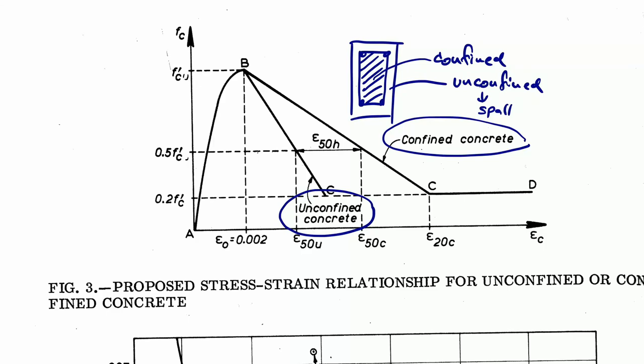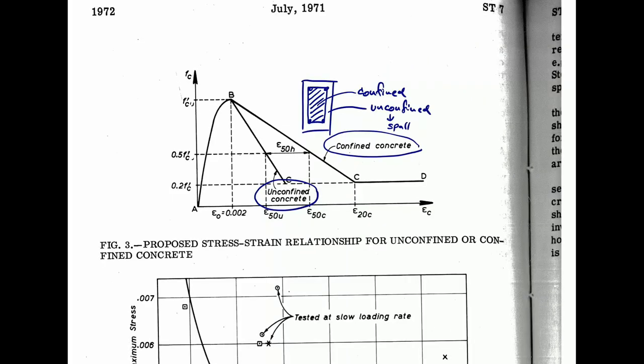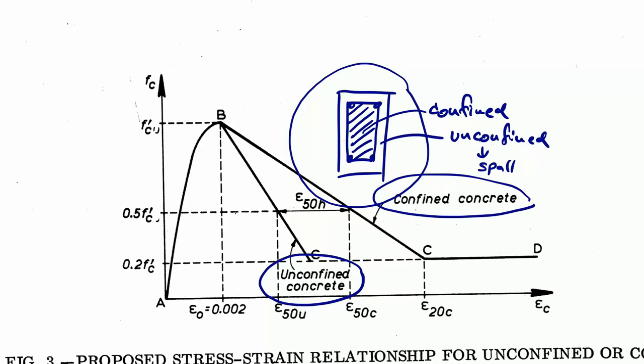That appears in many of the specimens you made for the advanced reinforced concrete structures course, which also shows the unconfined zone coming off. If you want to be very precise, you can make a numerical model of the cross section using a combination of confined core and unconfined concrete on the outside. If you want to be sloppy but conservative, that might be okay for design. You just want to spare the effort for some other procedure, so you can go ahead with the whole cross section being unconfined concrete.